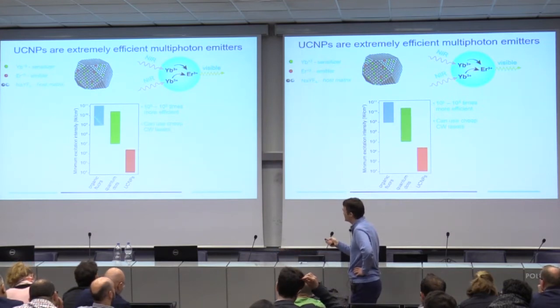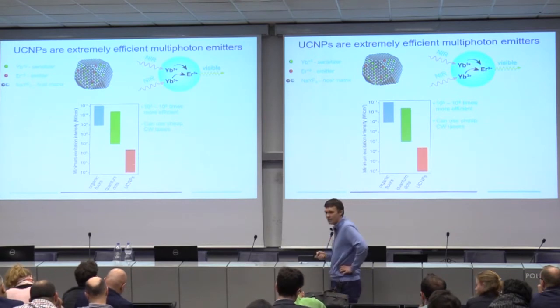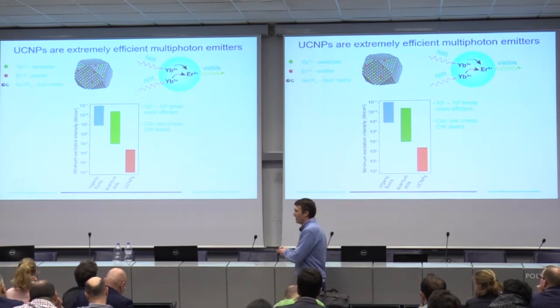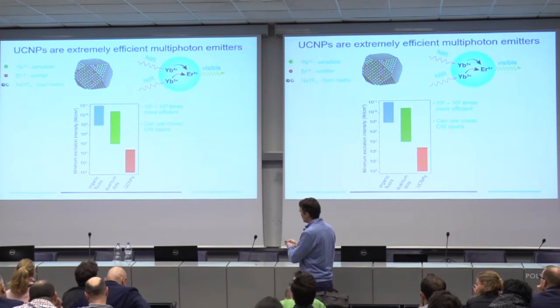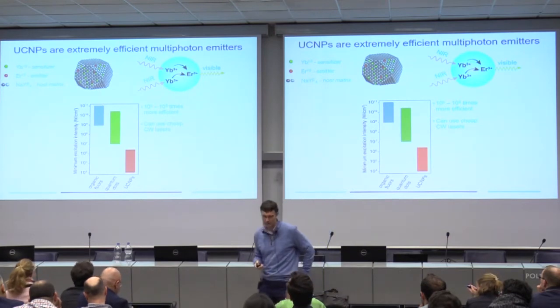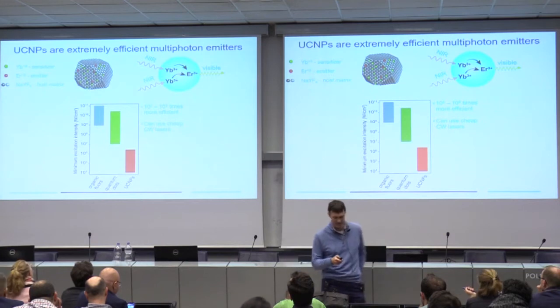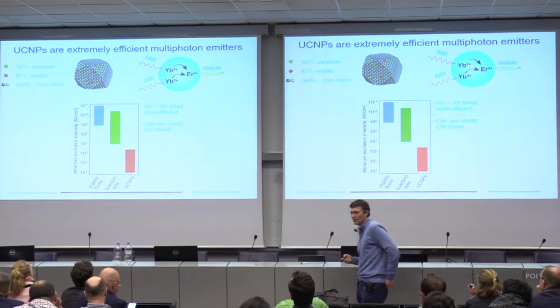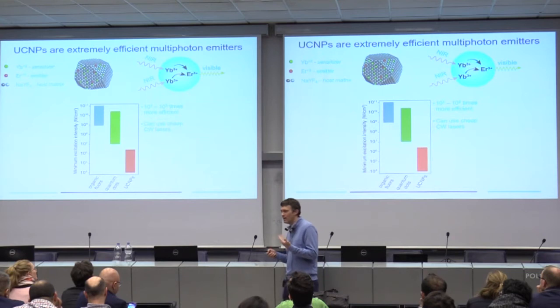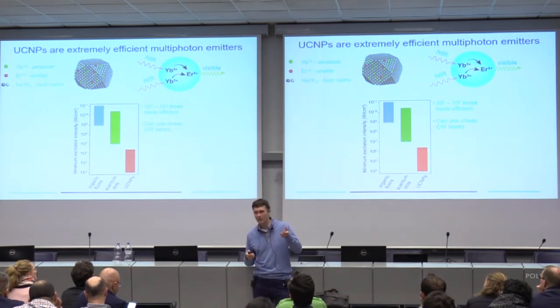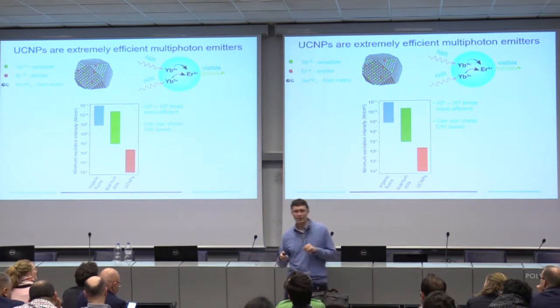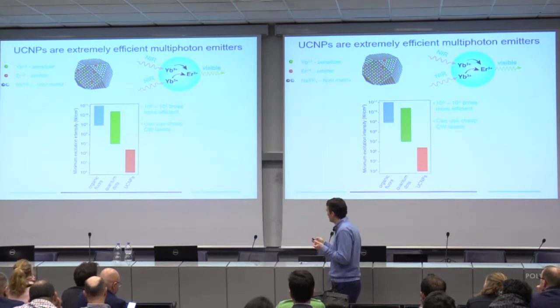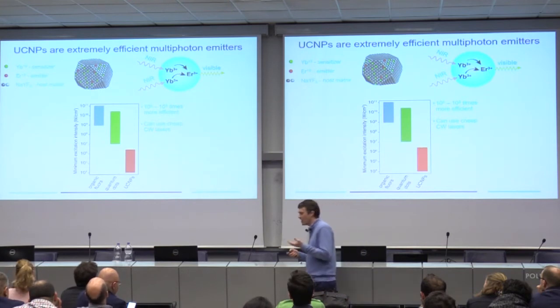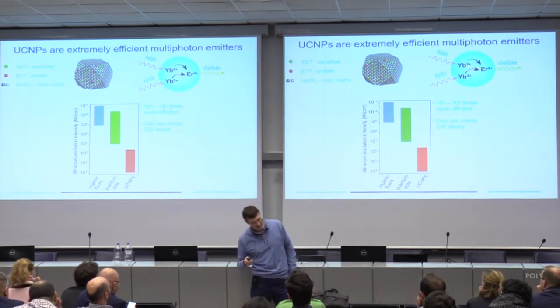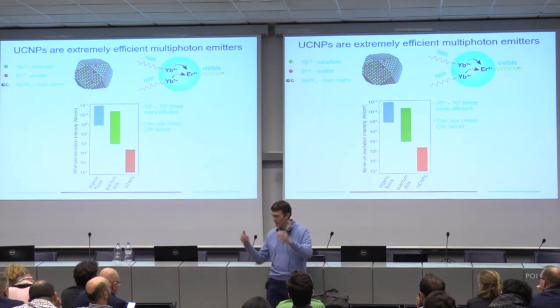And so here's a comparison for the minimum power needed to get a certain signal-to-noise ratio when you're using upconverters versus quantum dots and organic fluorophores and looking for nonlinear signals. What this means is that already with these upconverting nanoparticles, you can now use cheap, $300 Thorlabs diode lasers to do your nonlinear imaging, your multiphoton imaging, rather than a Ti-sapphire laser, right? As a colleague of mine, Bruce Cohen, likes to say, they took the $100,000 laser and put it in the nanoparticle.